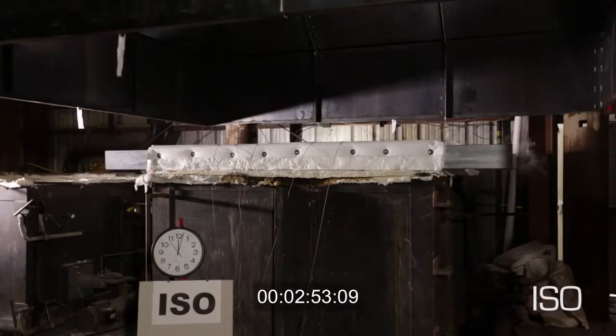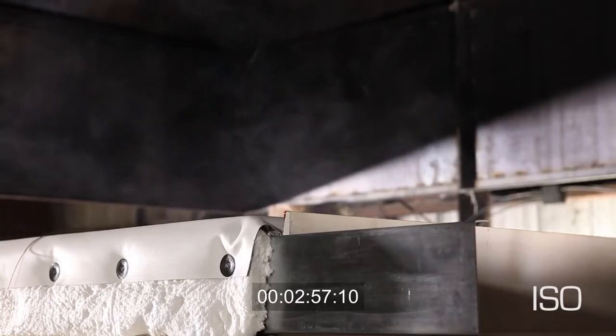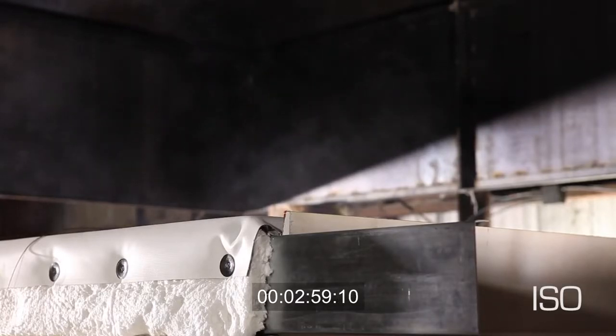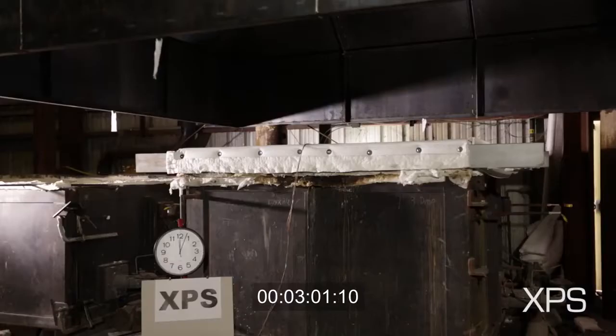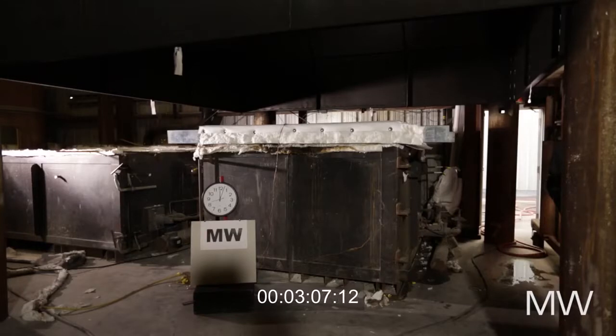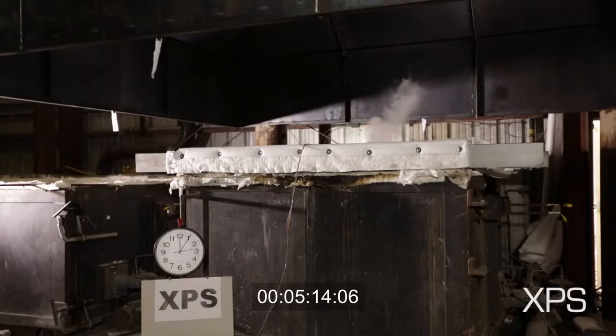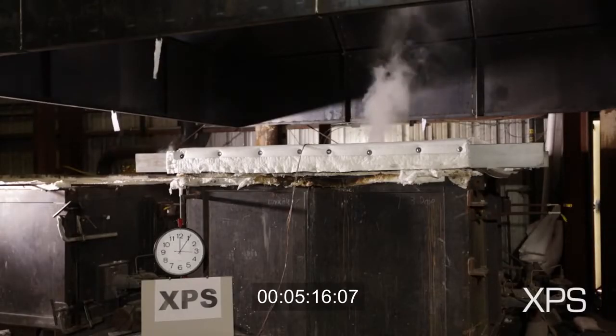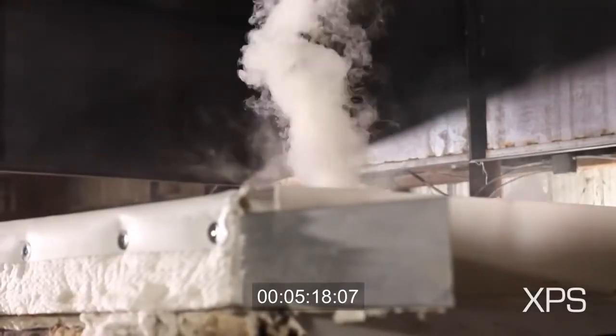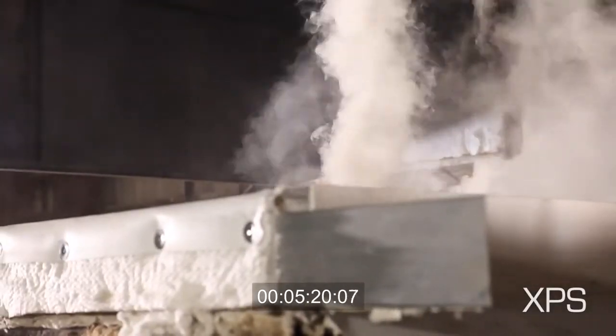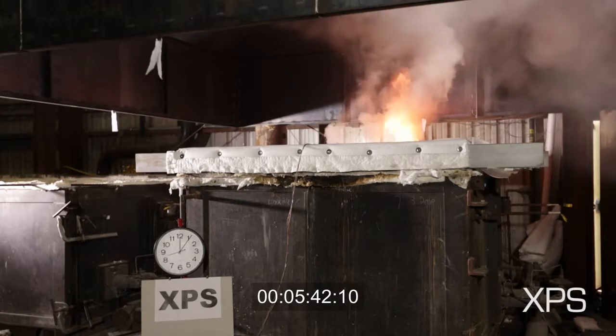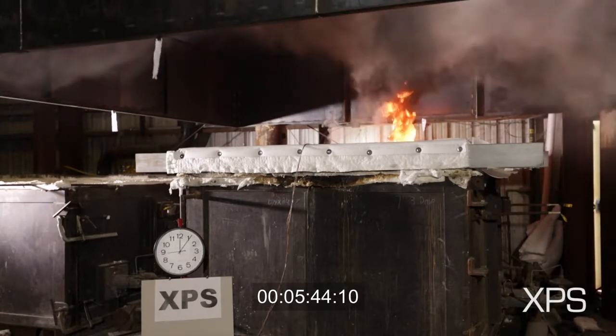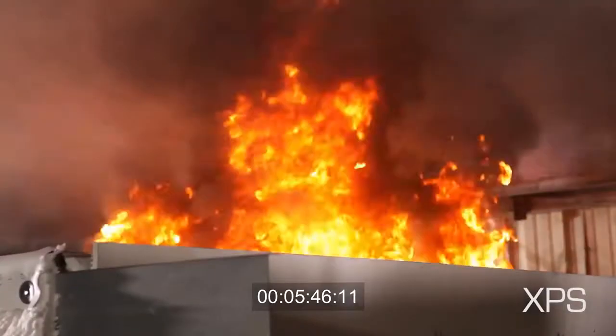Now, as we begin to approach about 3 minutes into the test, we begin to see some light smoke emitting from the isocyanurate material. That smoke continues to be emitted throughout the course of the test. Similarly with the extruded polystyrene, at this stage we are starting to see a light amount of white smoke. Once we reach about 5 minutes into the test, there is a fairly heavy amount of white smoke being emitted from the extruded polystyrene roof assembly, and at 5 minutes and 45 seconds into the test we see flame through.